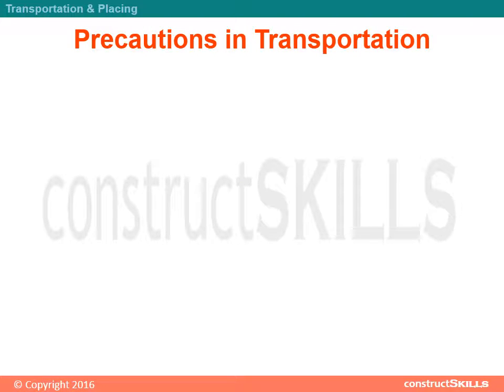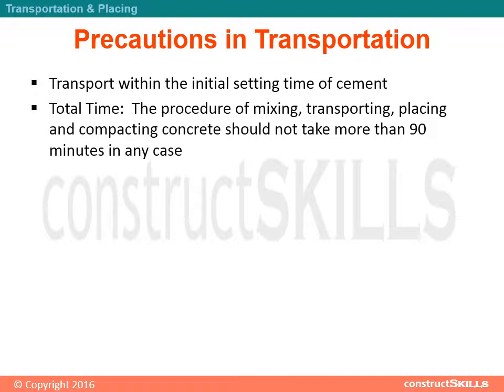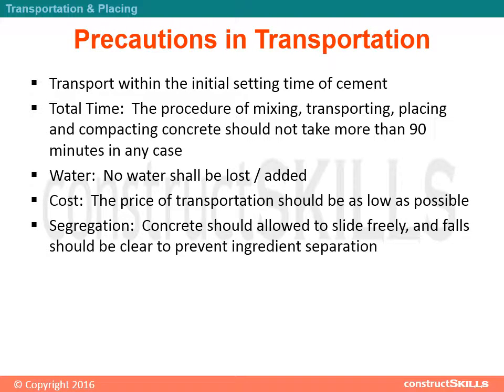Precautions in transportation: transport within the initial setting time of cement. The total time for mixing, transporting, placing, and compacting concrete should not exceed 90 minutes in any case. No water shall be lost or added. The cost of transportation should be as low as possible. Concrete should be allowed to slide freely and falls should be clear to prevent ingredient separation.